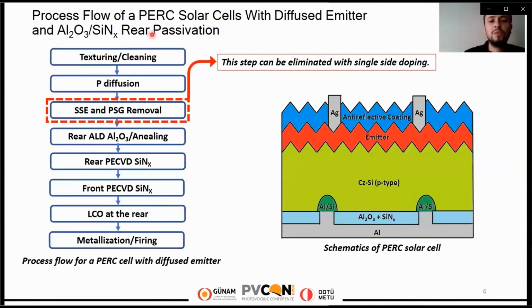Here you see a process flow of a PERC cell with diffused emitter and aluminum oxide rear passivation step. The process starts with the texturing and cleaning steps, followed by phosphorus diffusion. Since phosphorus diffusion results in N+ formation on both surfaces, a single-side etching process is needed to remove N+ from the rear side. The single-side etching can be eliminated from the flow if we apply an implantation method, because it allows single-side doping.